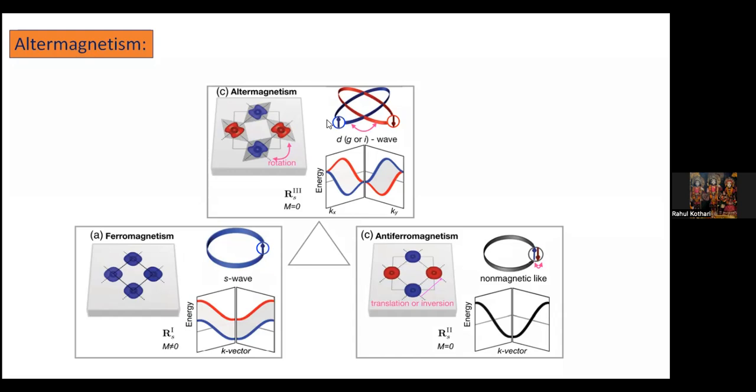But if you perform the same experiment on a magnetic material, you will have a contribution from the magnetization, and we call it the anomalous Hall effect. Subsequently, people have explained it in terms of Berry curvature, whether it is of internal or external origin. So this anomalous Hall effect, in a system which has no net magnetization, in principle you should not experimentally realize any anomalous Hall effect.